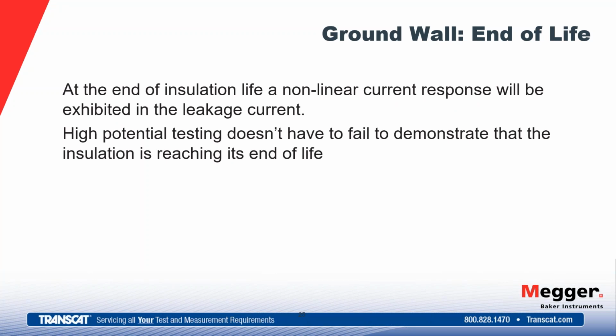Finally, here we bring ourselves to a higher voltage test. These are our indications of end of life if we're failing our ground wall tests here. At the end of insulation life, a nonlinear current response exhibits itself in the leakage current. So high pot testing does not have to fail to demonstrate that insulation is reaching its end of life.